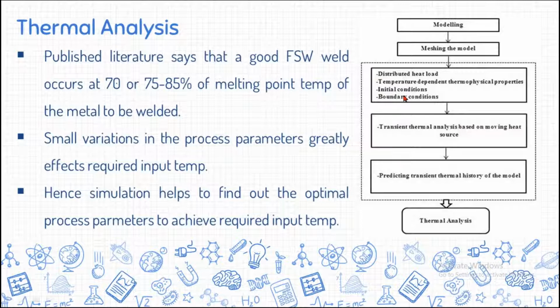It is always preferable to keep the initial boundary condition at room temperature, around 20 or 27 degrees centigrade. So this is about the thermal analysis. As I already told you, around 75 to 85% of the melting point temperature of the metal to be welded is the required temperature for a good friction stir weld. Small variations in any of the process parameters greatly influence this input temperature. Hence, this simulation will give you optimal process parameters to achieve the input temperature.